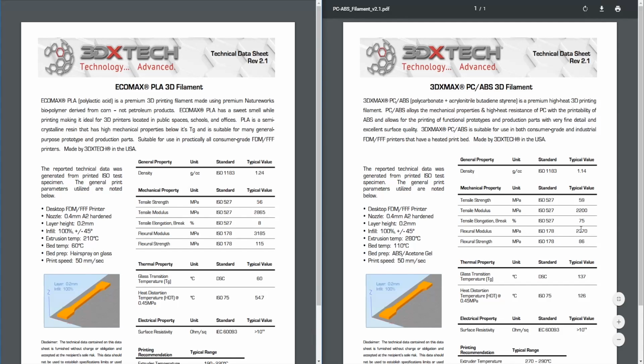Here we see that the polycarbonate ABS mix, 59, a little bit stronger. That's interesting. Tensile modulus 2200. Whoa. Tensile elongation at break 75% at that much stiffness. Wow. That's amazing. That might be something to think about. This might be one to look at. The polycarbonate ABS mix, the 3DXMAX from 3DXTech. Wow. Same, even stronger material, almost as stiff, but what is that?